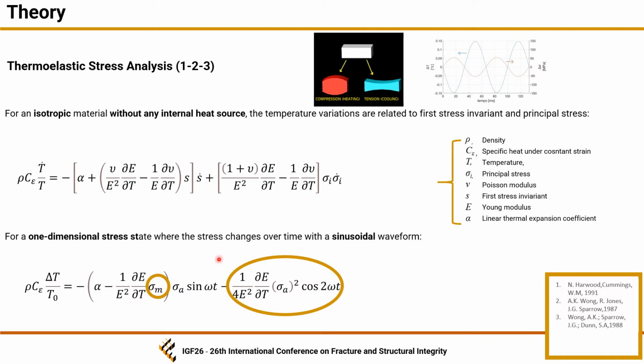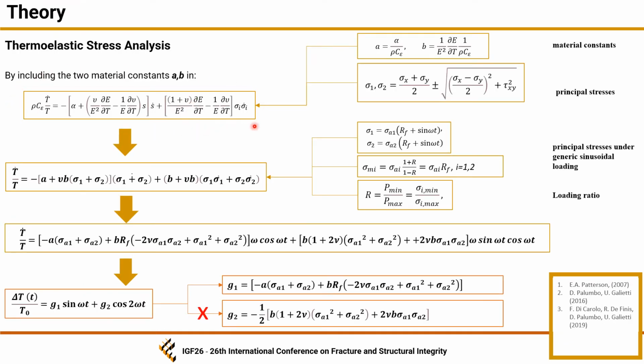time with a sinusoidal waveform, we can see that there is a mean stress dependence that arises when the material mechanical properties such as Young's modulus depend on temperature, and it is also interesting to observe another term running at twice the mechanical frequency. By considering the previous formulation and taking into account the material constants and the principal stresses, and by considering that the principal stress under generic sinusoidal loading can be written as a function of its amplitude and loading ratio, it is possible to obtain this wide expression for the time derivative of temperature variation,